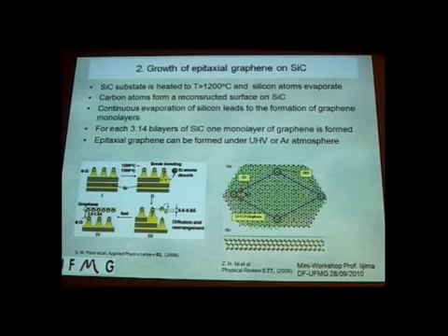So this is a view graph of the mechanism of formation of the graphene film. You have the silicon carbide, you heat treat, then the silicon atoms desorb, and you start to have a graphene film which is reconstructed, and eventually you form more than 1 monolayer. And this on the right is the crystallography match of the graphene on top of the silicon carbide. And actually what we have is a supercell of graphene on top of silicon carbide. As I'm going to show, this is not a perfect graphene film.